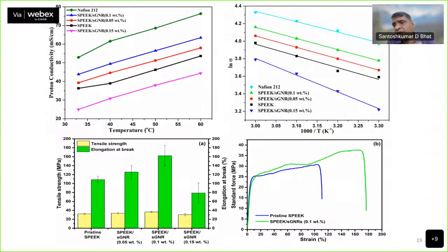And then a major point is ionic conductivity, where we can see the activation energy for ionic transport, where we see the conductivity in relation to temperature. And then we also look at the mechanical property of the membrane, which is very, very critical. So when we do the tensile strength test, you can see the mechanical strength of the membrane in terms of elongation, in terms of stress applied. And then we have a stress-strain curve, where we see how the overall mechanical property of the composite changes compared to the pristine membrane.